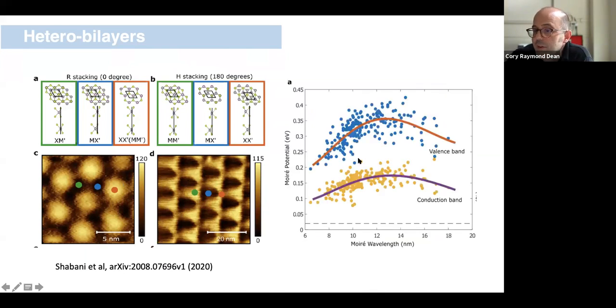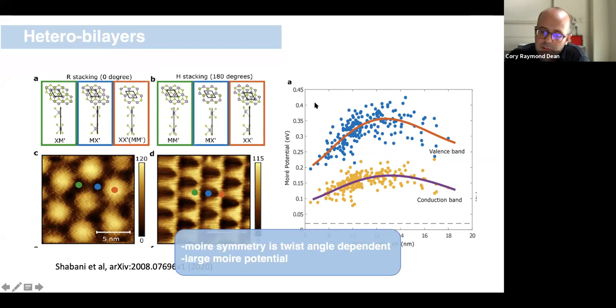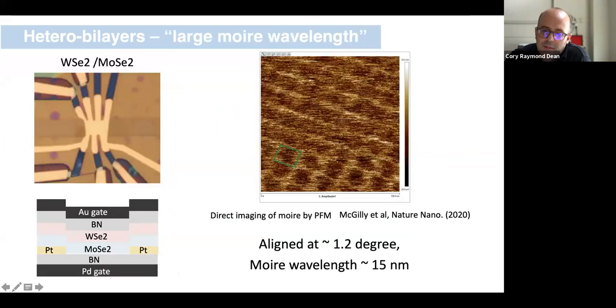And also you can get really dramatic effects in terms of the effective magnitude of the Moiré potential that exists in these heterobilayers. So in this particular system, they identified evidence that the Moiré potential could be as large as several hundred meV. That's much larger than we anticipated we could get in, for example, twisted bilayer graphene or graphene coupled to BN, et cetera. One of the consequences of that we may have seen already.